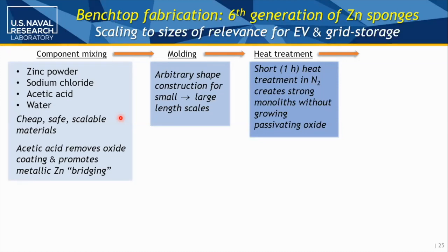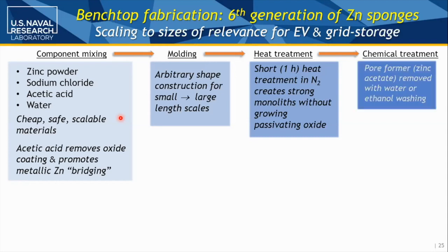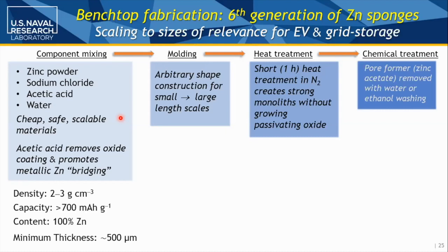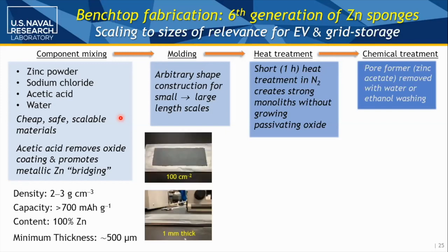Under nitrogen, you're getting your bridges between the zinc particles without the elaborate treatment that we described in our first paper in 2014. And then you just remove the porogen, in this case being things like salt, with water and ethanol washing. So we're getting in that sort of nice sweet range of 2 to 3 grams per cc, so 30-40% fill factor, getting high capacity. And this can be done without having to electroreduce any thermal oxide on the system.